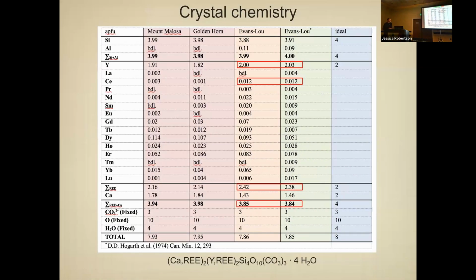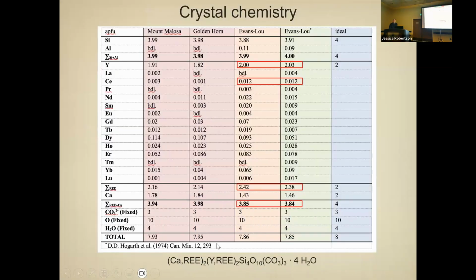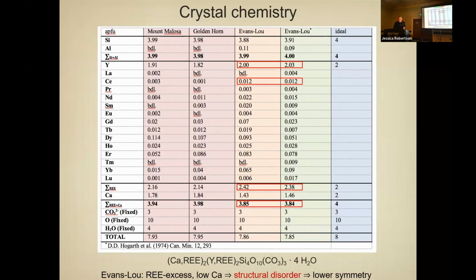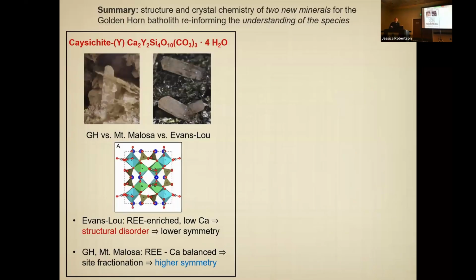And so what this tells you is that we need to write the formula with mixing of rare earths onto the calcium site. This gives rise to an equal electron density of these two sites and is then responsible for the structural disorder and the lower symmetry. So we got it. This was just pieced together about a week or two ago, and we're just writing up the manuscript.